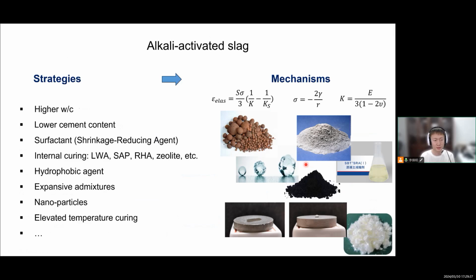There are different ways to mitigate the shrinkage, but I want to say that all the methods must have their own mechanism. So we need to see which method changes which parameter. It is related to the elastic modulus to make it stronger, or it's related to a lower capillary pressure, or lower saturation degree, or a coarsened pore structure, which means a larger pore size, or something else. So anything must have its own mechanism.